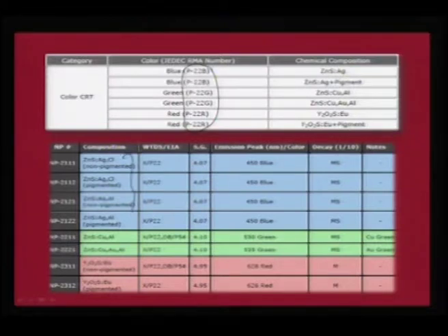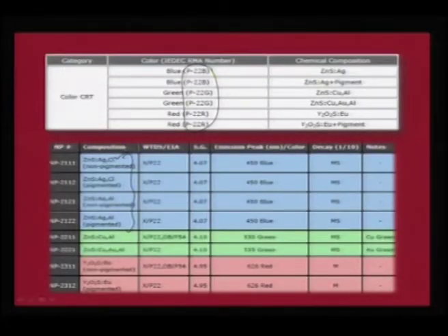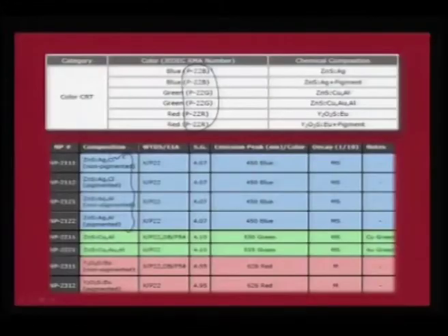As you would see here, in all these blue emitting phosphors it is silver, but along with silver you also see a chloride ion that is doped, which is considered to be a coactivator. If you want a very strong fluorescence, not only do you dope with silver, which is the actual dopant and activator, you also use chloride as a coactivator, which improves the efficiency of these compounds.